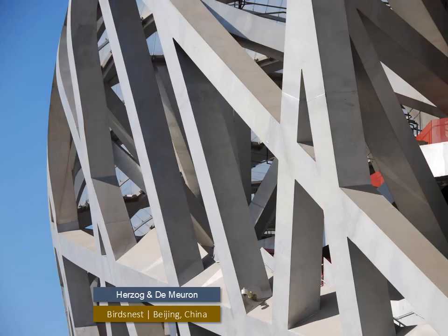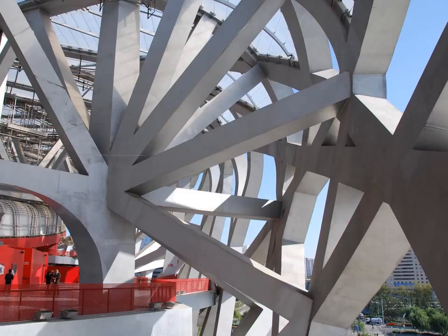The custom curved box section structure of the Bird's Nest Stadium needed a heavy-duty corrosion protection system, but due to the sheer size of the members, hot-dip galvanizing was out of the question. The surface of the members was first roughened, followed by 2 coats of a spray-applied intermediate layer of epoxy micaceous iron oxide, followed by a spray-applied metallic gray fluorocarbon finish.